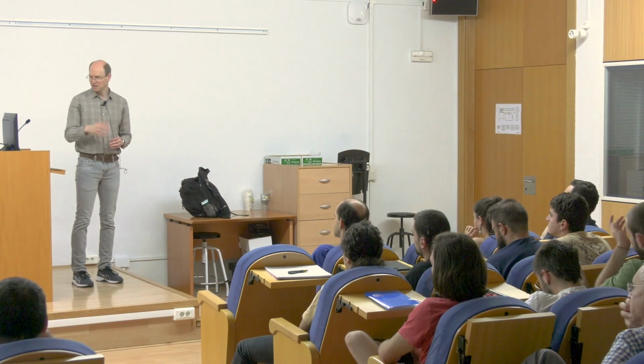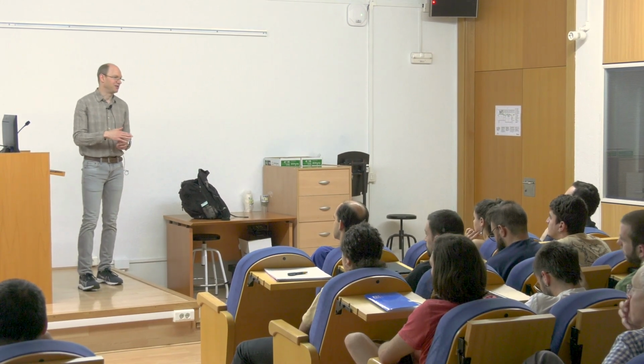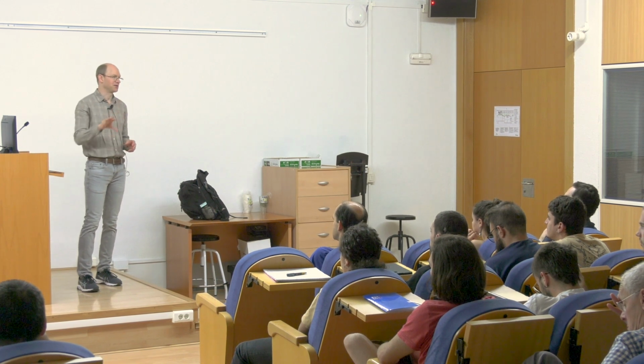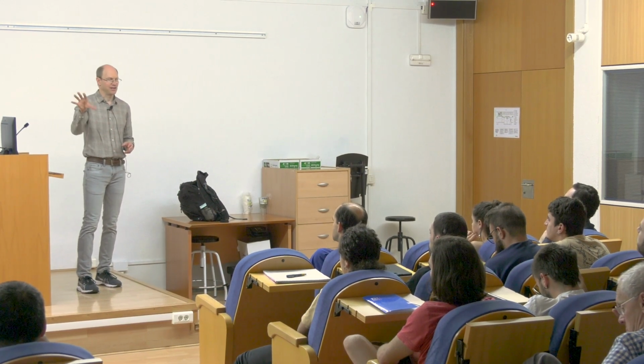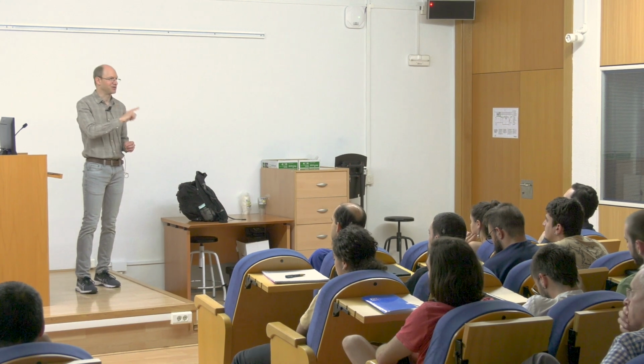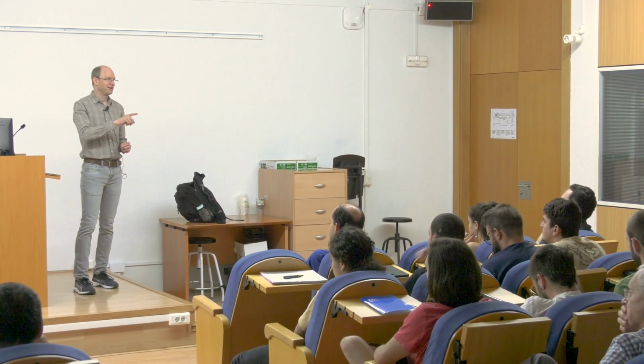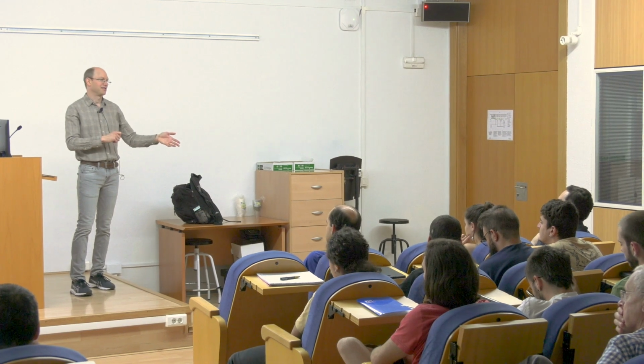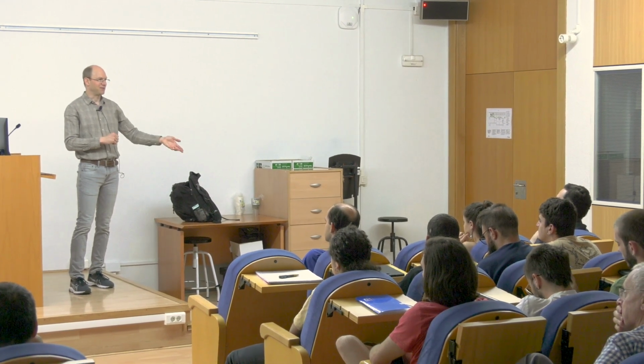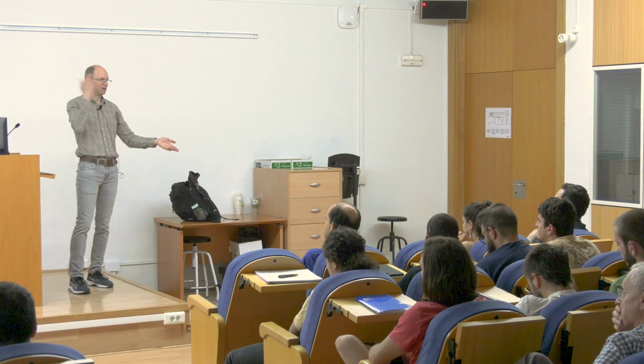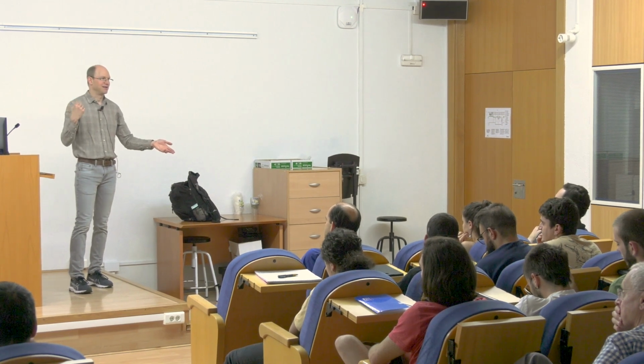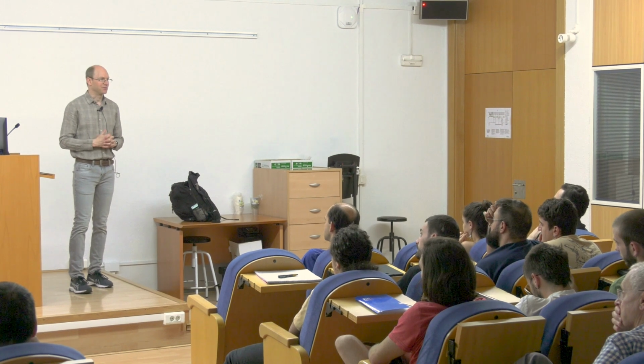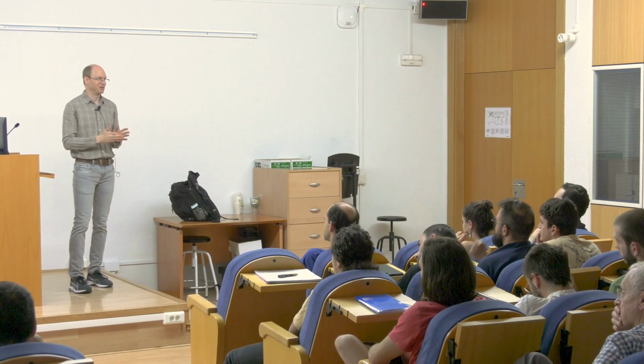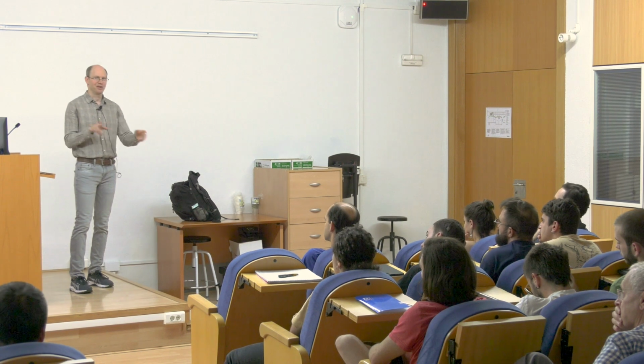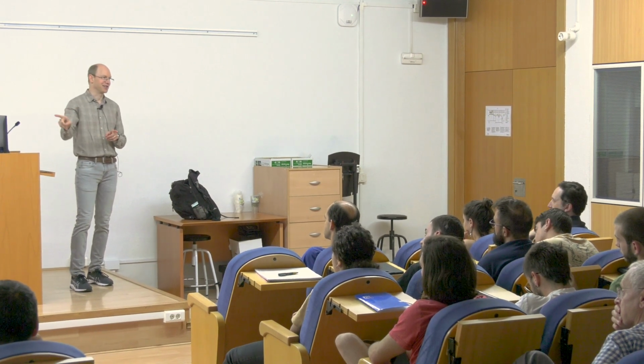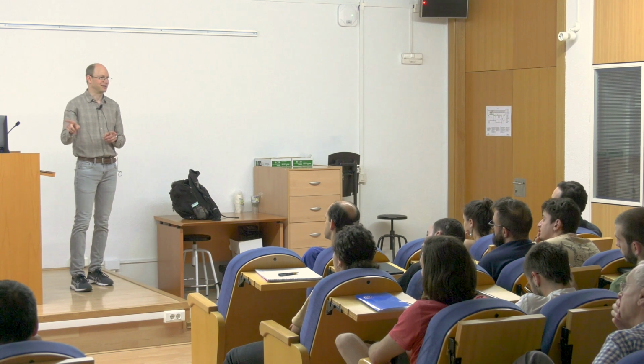If you just cool those systems down under the pressures and temperatures in which the experiments were done, and external fields, even to arbitrarily low temperatures, you will not get that charge ordered state for the tantalum sulfide. You will not get that metallic ferromagnet for the lanthanum calcium manganese oxide, or the ferroelectric state for strontium titanate. So cooling alone won't do it. You've got to have the light, unless you go off in a different direction, like you apply strain or another field, like an electric or magnetic field.